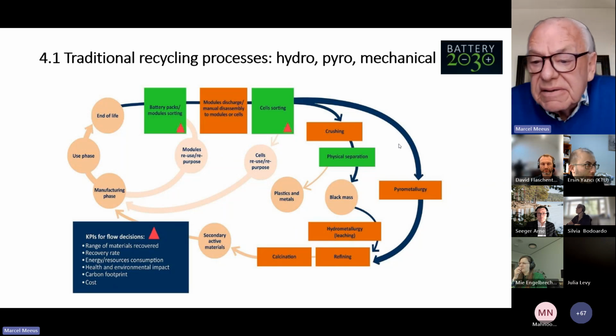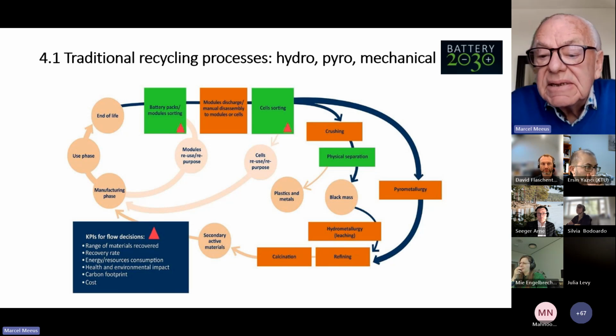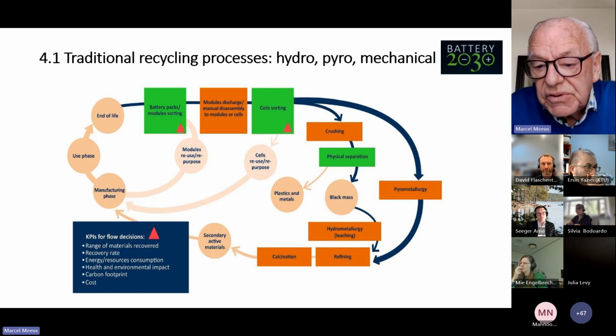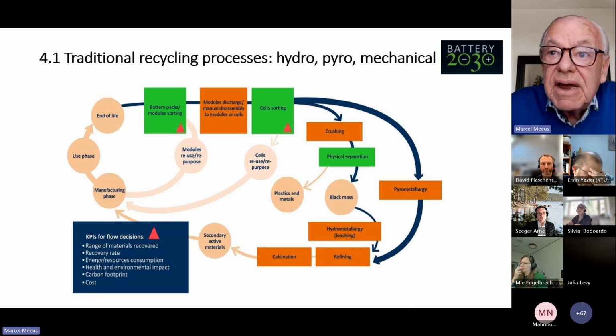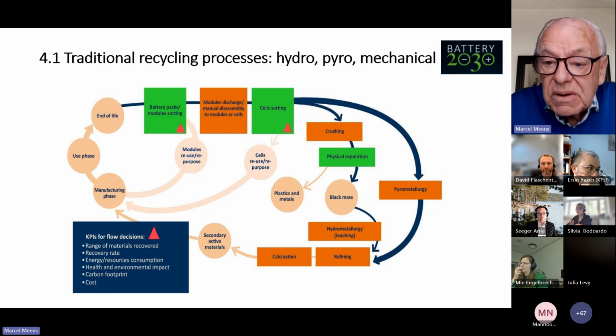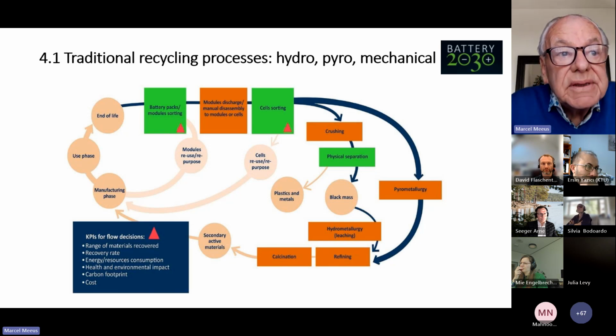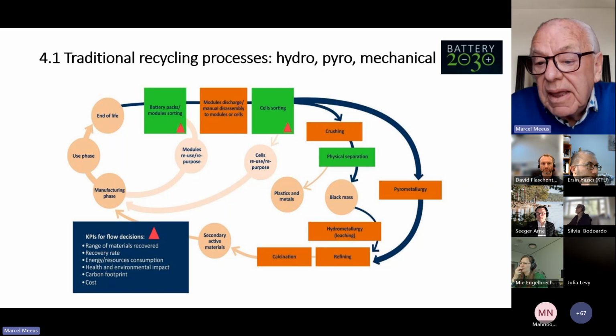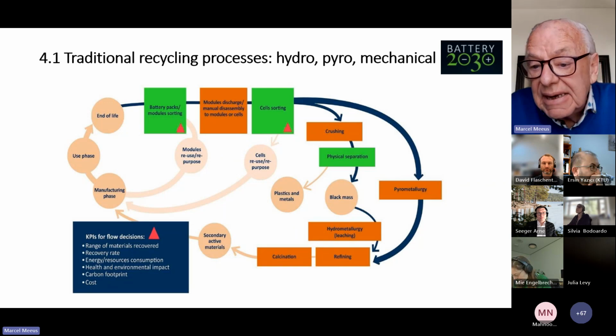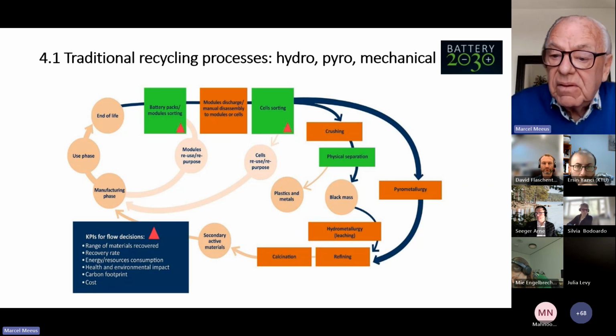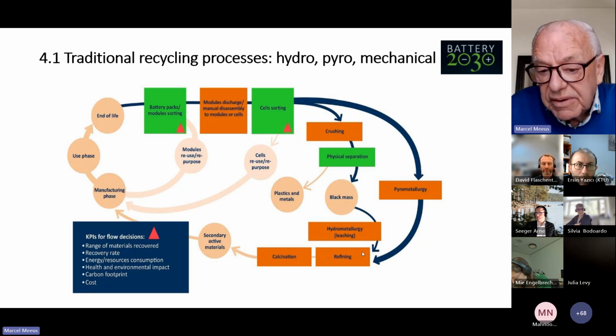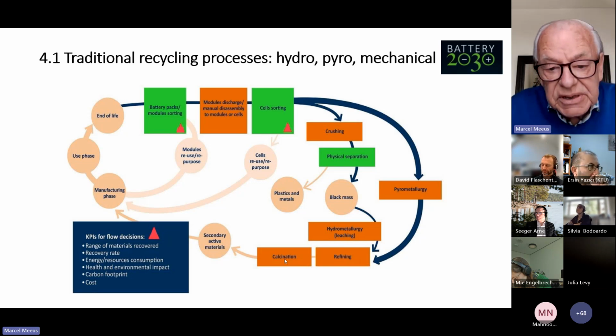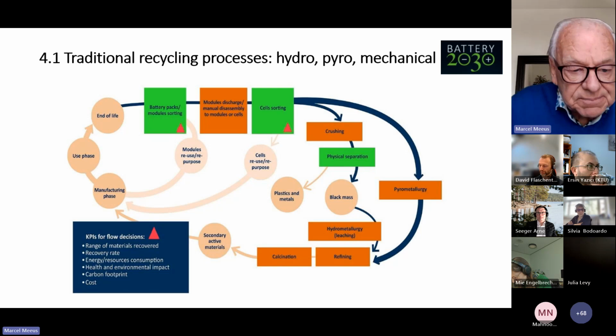Pyrometallurgy, in fact, does not use that shredding process. The cells go immediately into high temperature furnaces, and this gives rise to a white alloy, and that white alloy contains the nickel, the cobalt, and the copper. There are slags, and those slags contain aluminum, manganese, and lithium. Those slags are also treated to recover the lithium, and those products go into further refining, followed by traditional calcination and reuse in the system.